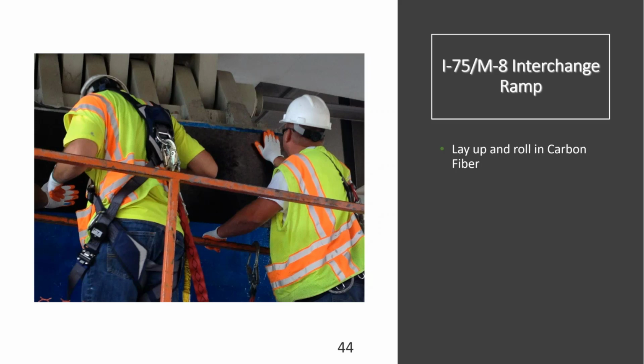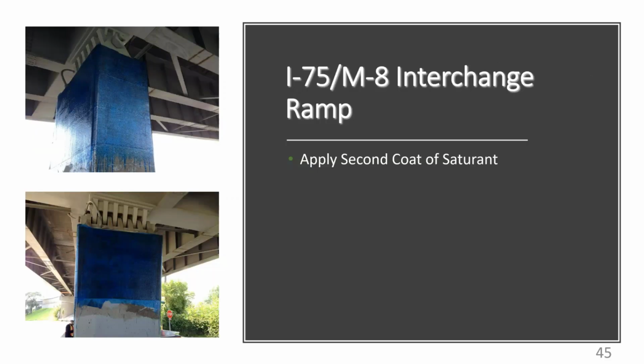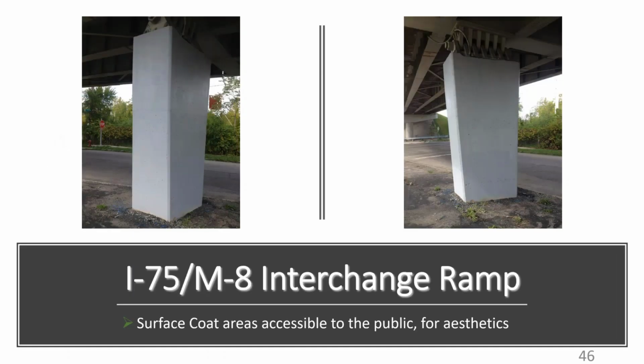After the fabric is set in the saturant, it is then coated with an additional layer of saturant to finish encapsulating the fibers. Lastly, since this was adjacent to traffic, we decided to coat the entire column with a colored concrete surface coating. And as you can see in the picture, you can barely see where the repair area was.